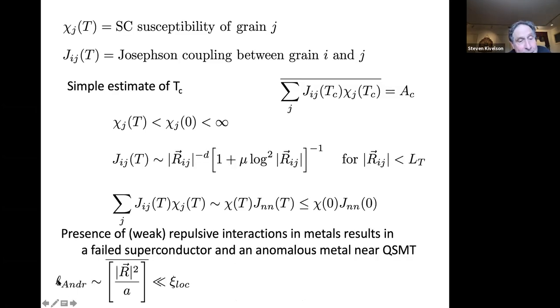On the other hand, there's another length scale that comes into this problem, which is the length scale over which electrons Andreev scatter off of grains. And that's simply geometric. That's the square of the distance between grains divided by the radius of the grains. So we can certainly arrange to have the grains be close enough to each other that this is much less than the localization length, in which case this length scale precludes localization. I don't know what happens at length scales beyond this, but the theory that you've used in order to derive localization is wrong past this length scale. And yet the system's not superconducting.